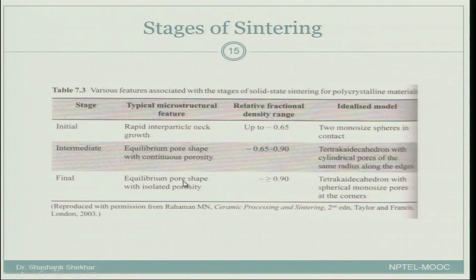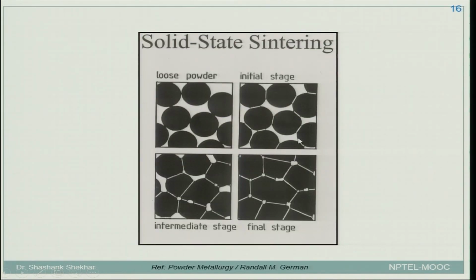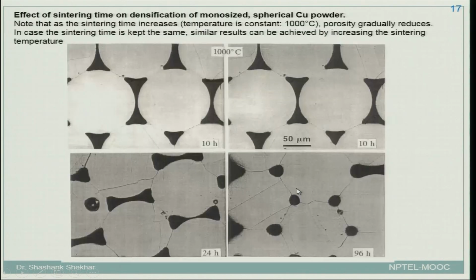In the final stage, the equilibrium pore shape has isolated porosity, and you may get a fractional density greater than or equal to 0.90. Tetrakaidecahedron grains again, with spherical mono-sized pores at the corners, is the idealized shape. This is a schematic of what is happening in the different stages. You have loose powder, then the initial stage where necks grow, and in the intermediate stage you have a network of pores. In the final stage, these are the pores at the corners of the grains.